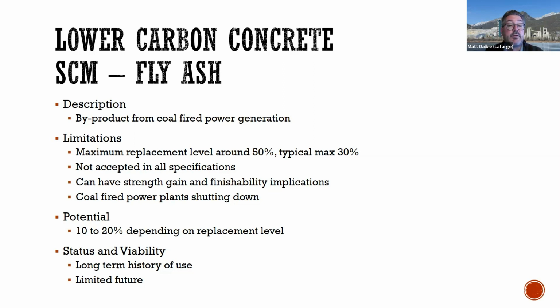So that's something that we're dealing with as an industry. Over the last couple of years, fly ash availability has become much more constrained, so that's something to be aware of. And as far as the potential reduction of CO2, it's around between 10 and 20%, depending on how much you replace. But it has been around for a long time, but has limited future applicability because of those coal-fired power generations shutting down. But the industry is taking steps to address that by recovering wasted fly ash that had